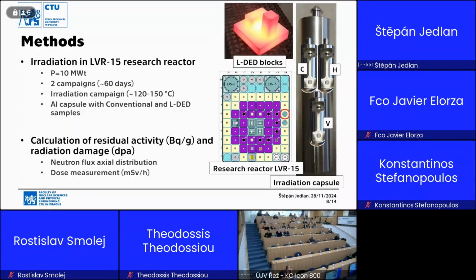And 5 samples of each type of material were put into the LVR-15 research reactor at position H6, which is circled by the red circle on the slide. We irradiated those samples for about 60 days at 120 to 150 degrees Celsius. After that, the samples were taken out, and there was a dose measurement. There were a few calculations that we did. Mainly, Jaroslav Šoltes did the calculations for the residual activity and for the axial and radial distribution of neutron flux. Based on these data, we are able to do the calculation of residual activity and radiation damage.